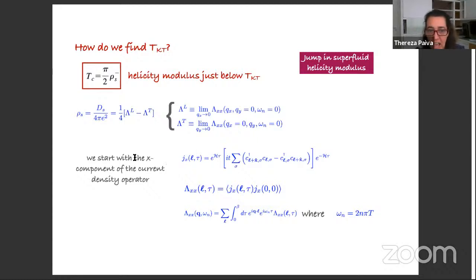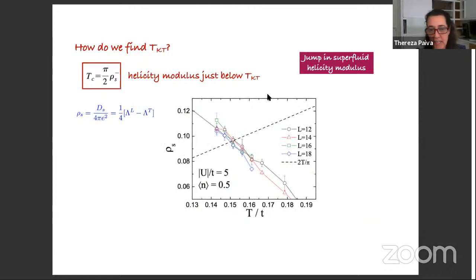So we start with the x component current density operator, and then we get the current-current correlation, and then we Fourier transform, and then we take the q going to zero limit in x and in y separately. And then from this, we get the helicity modulus. And this is a plot of the helicity modulus. And here is the dashed line that is the 2T over pi. And so here where they meet is the Kosterlitz-Thouless transition estimate. And we do see that if we take large enough system sizes, there is not much fluctuation here. So they pretty much agree, and we can use this variation as error bars.